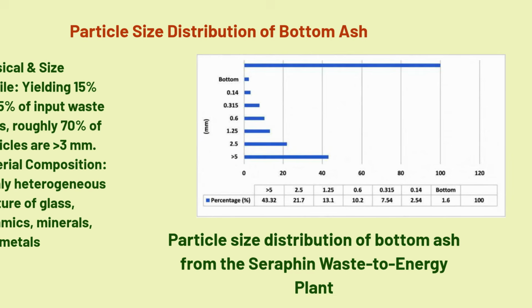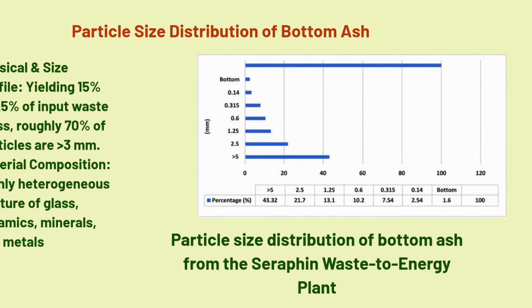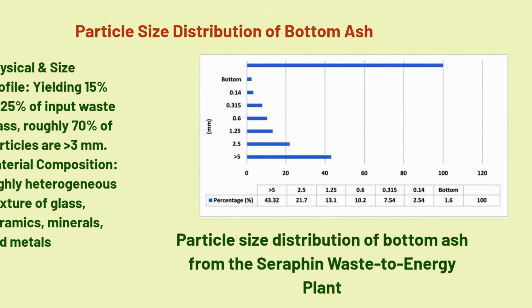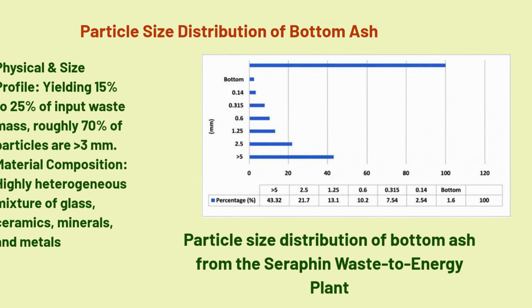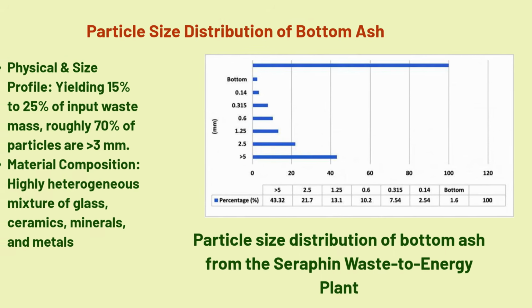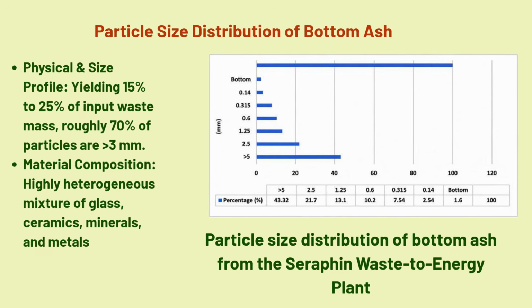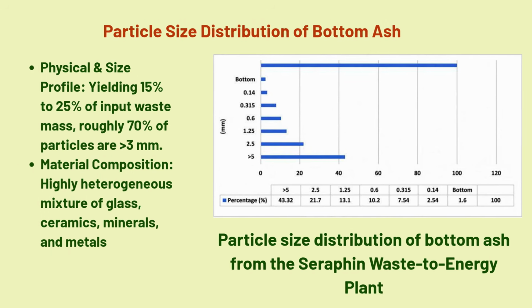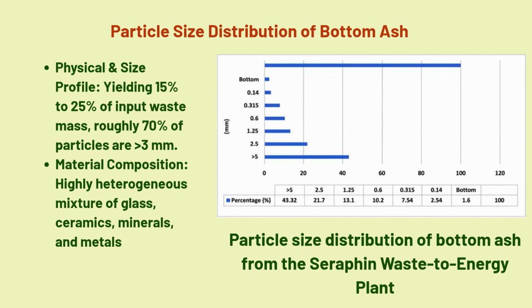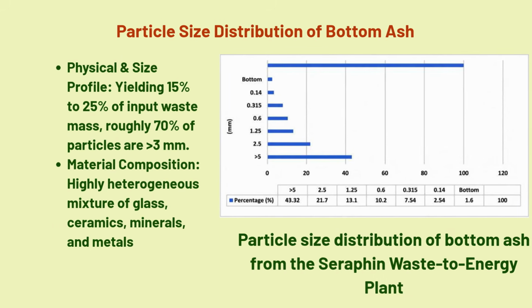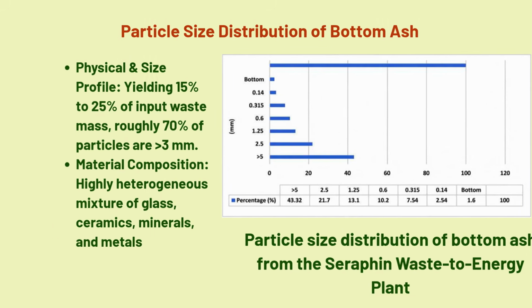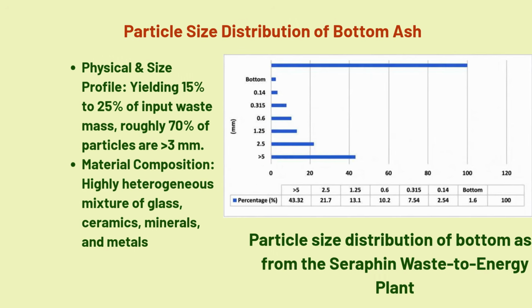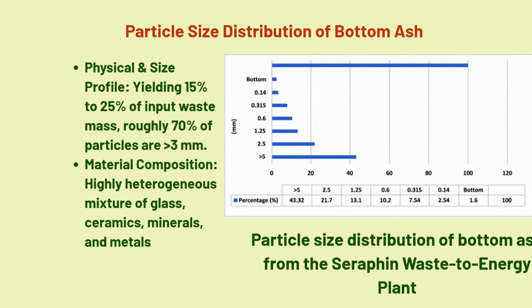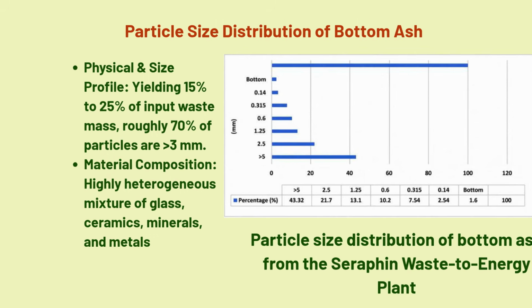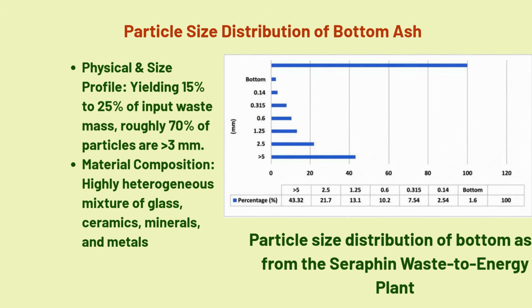First, let's look at the particle size distribution of bottom ash. Bottom ash accounts for approximately 15 to 25% of original waste mass, as shown in the chart. Around 70% of particles are larger than 3 millimeters, with the largest proportion belonging to particles larger than 5 millimeters.